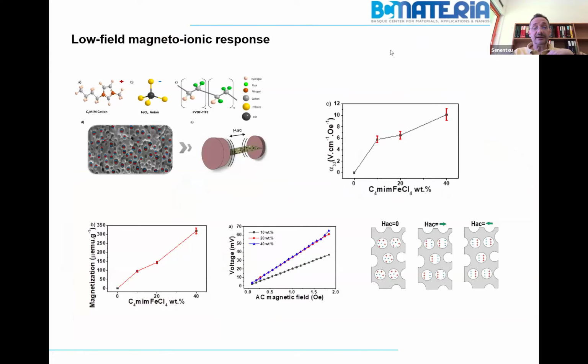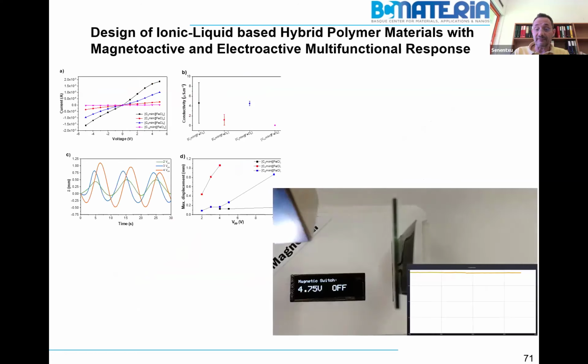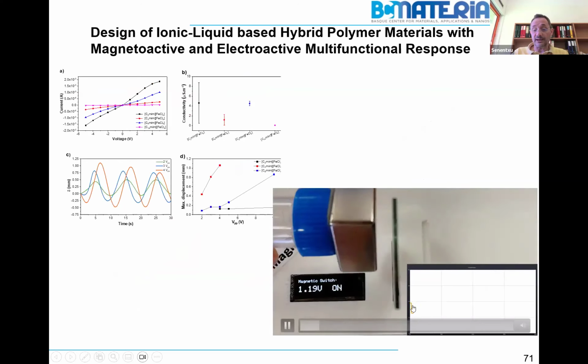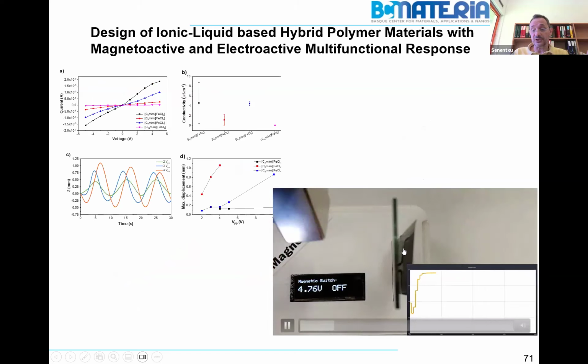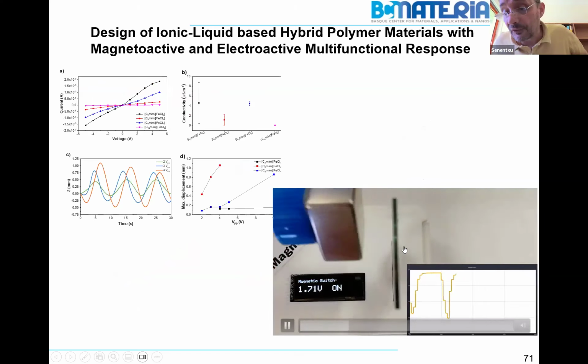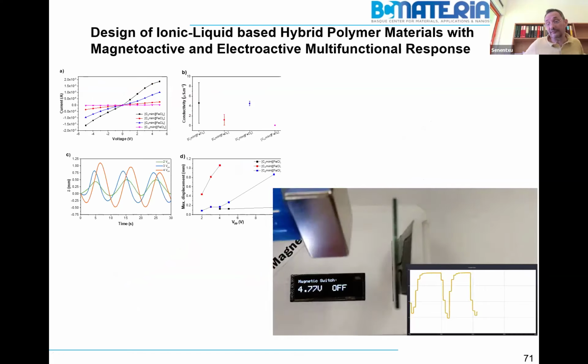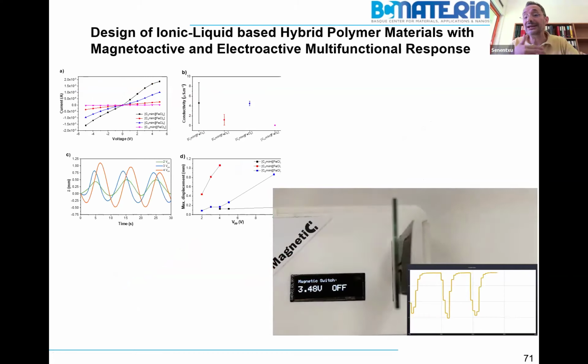The same, just by changing the anion and introducing a magnetic particle. The same is exactly the same. Magnetic particle, no, a magnetic atom. Magnetic response is not high. You cannot compare with the nanoparticles, but it is high enough to have, for example, magnetoelectric response, as you see, and measuring the deformation of a material to a magnetic field. That means measuring indirectly the magnetic field, okay?